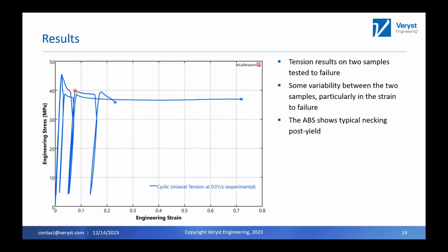You can see here there is a little bit of noise, but with how small those samples were, they were 3 millimeters wide in the gauge section, and on the order of a millimeter thick, this is not very much noise, so no issue with data fidelity. And if you're not familiar with ABS, this is very typical material where you see necking and softening after the yield. You get that, and then a stress plateau.